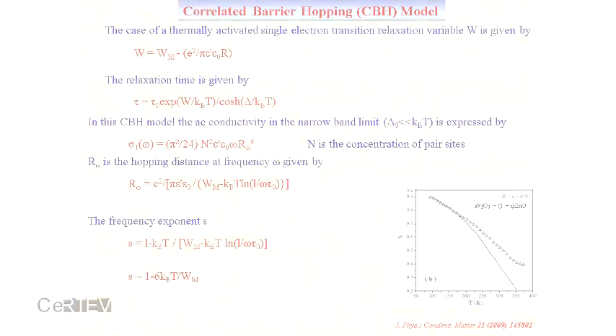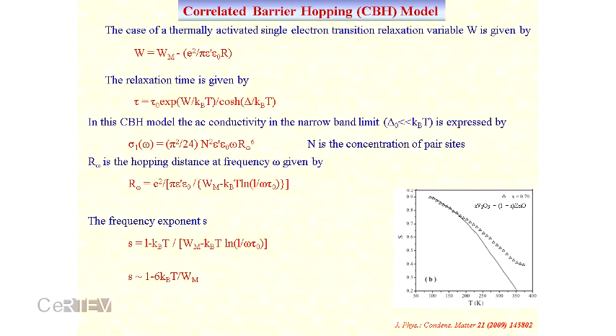And another model is the correlated barrier hopping model. In the barrier hopping model, without tunneling, the electron can hop, as I have told earlier. This model predicts the conductivity in this form and the exponent in this one. Here also the conductivity exponent decreases with temperature, but it can fit only a limited temperature region. Beyond that temperature, this model is not valid. So hopping is valid only at high temperatures, but the large polaron tunneling is valid for the entire temperature range. So I have described the DC conductivity as well as AC conductivity considering the polaron models.